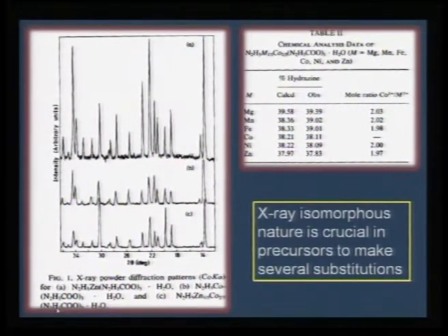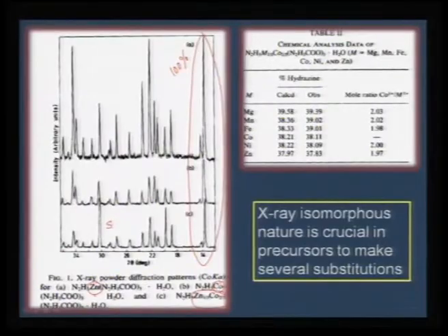And typically, if you look at the X-ray mapping, I just want to draw your attention to this first peak, which is coming at 14 degrees when you do the powder X-ray diffraction. As you can see here, this tall peak, which is usually referred to as the 100% peak, is coming at nearly 14 degrees, and irrespective of what the metal ion is, whether it is zinc or cobalt, you still see the same crystal structure. And because of this crystal structure, it is possible for me to make zinc and cobalt together, which is nothing but your C. So, when I make a comparison between A and B, it gives me the possibility to go for the solid solution, which is C.